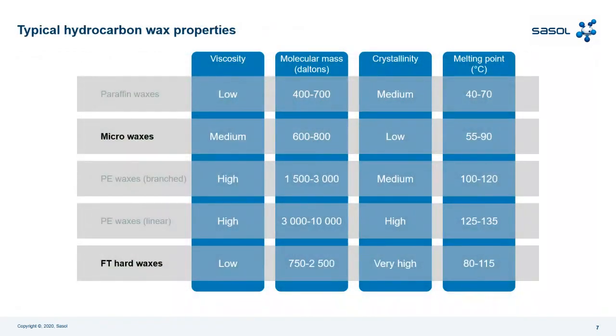A quick overview of the waxes that I will present today. We will present microcrystalline wax and Fischer-Tropsch wax, as I mentioned. Microcrystalline wax has medium viscosity and a molecular mass from 600 to 800 Daltons. The crystallinity is low, and the melting point is from 55 to 90 degrees. Fischer-Tropsch waxes have very low viscosity and a molecular mass from 750 to 2500 Daltons. Crystallinity is very high, and the melting point is from around 80 to 115. This is an overview to explain the difference from, for example, paraffin waxes that Sasol also has, and PE waxes.